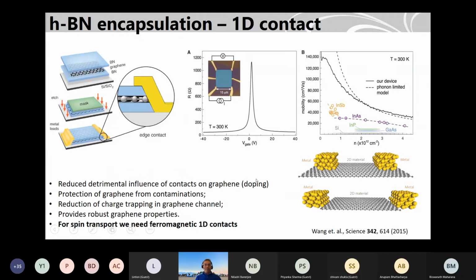So how to get very high quality graphene? That is more interesting if you want to do spin transport in the ballistic regime. So you need high quality graphene. High quality graphene can only be obtained if you encapsulate graphene completely inside the boron nitride. So if this is the graphene, you have boron nitride on both sides. And then if you do that, you don't have any chance to contact from the top because boron nitride is an insulator. So you have to find a way to contact at the edge.